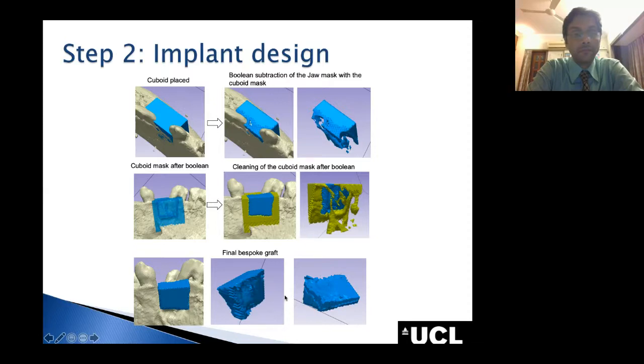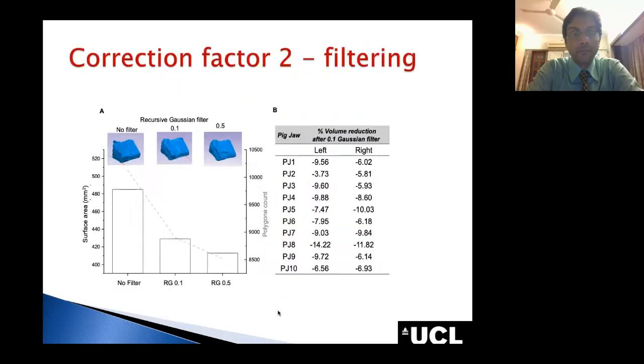Therefore, we need something to smooth it and to make the surface really smooth. And for that, we use a recursive Gaussian filter. You can see in this graph that as we apply the recursive Gaussian filter, even though we are just using a strength of 0.1 or even 0.5, the surface area of the graft will significantly decrease. And so will the polygon count, which is basically the information on the surface, which is, for example, this little part. This will really decrease.